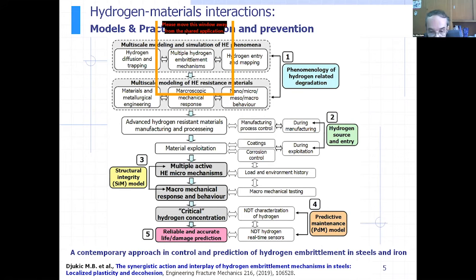In our recent review paper published in Engineering Fracture Mechanics, we proposed a 5-step approach in analysis of hydrogen materials interaction, which consists of phenomenological analysis of hydrogen-related degradation phenomena, and different experimental and modeling approaches in order to finally reveal the hydrogen embrittlement mechanism active in a particular material. Next is the analysis of hydrogen source and entry, where corrosion is the main process which provokes hydrogenation of material during the exploitation of various industrial components. Based on such analysis, we develop a structural integrity model based on the multiple hydrogen embrittlement mechanisms active in steels and other materials, connected with the micromechanical response and behavior upon reaching the critical hydrogen concentration in the material.